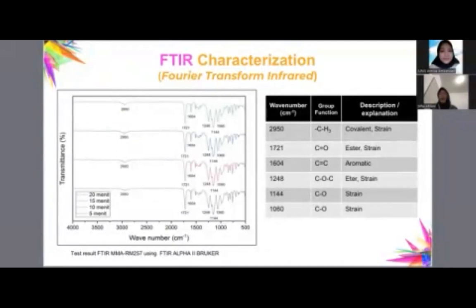In this spectrum, there is no absorption peak at 1,670, which indicates the absence of a C=C double bond. Besides that, there is no absorption peak at 3,100, indicating the absence of the phenyl belonging to RM257. So it can be concluded that MMA has polymerized to form PMMA and binds to RM257. Based on the graph, the spectra of the four samples are similar or not much different. This indicates that the time difference in UV curing does not affect the wavenumber, but slightly affects the intensity value of the FTIR spectrum of PMMA RM257.